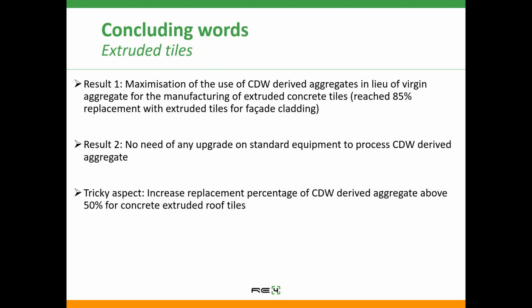Resuming some concluding words. First result, the maximization of the use of CDW derived aggregates in lieu of virgin aggregate was achieved with a very, very interesting percentage of 85%. That has been achieved for extruded tiles to be used for facade elements. This percentage is much higher than the one reached when we had to deal with concrete roof tiles, because for concrete extruded elements for facade wall, there isn't actually any standard which prescribes lower thresholds in terms of flexural resistance.